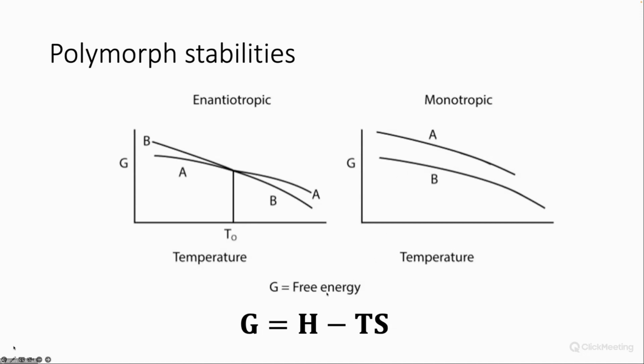This all relates, of course, to the free energy. So it all relates to Gibbs free energy, which is, as you know, a function both of the enthalpy of the system and of the temperature and the entropy of the system. So the entropy is really a determinant here, because of course that is multiplied by the temperature, and that will change significantly as we heat the system. So if we have a polymorph with a very high entropy, it's going to have a fairly steep curve here, and it will sort of overtake the other forms as we heat them. It will become the most stable form at higher temperatures if it has a larger entropy.